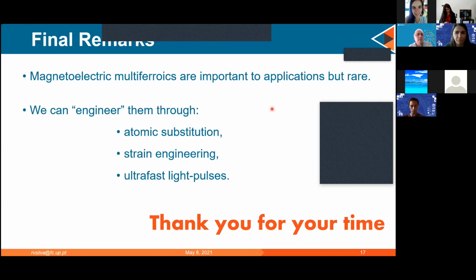So when you apply this terahertz pulse, does it also affect the substrate? Does the substrate also play a role in the study, or does it not, other than causing the strain? I mean, what is the effect of the substrate? Yeah, the substrate was chosen in order to induce that strain that you need for, in this case, the gadolinium manganite to become ferroelectric. So of course, if you choose another substrate, this will not occur in this way.